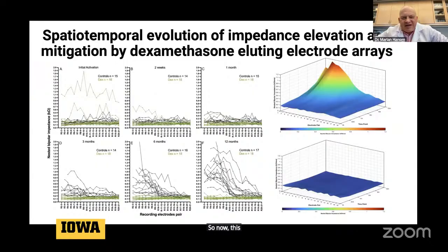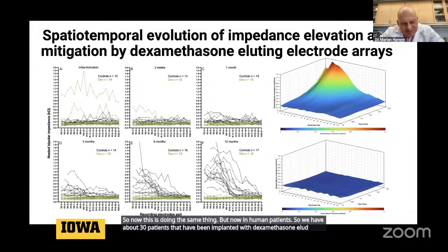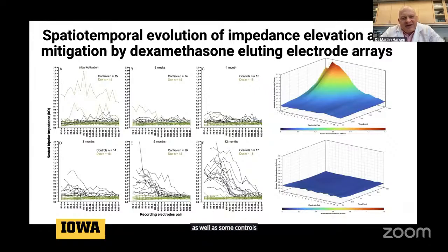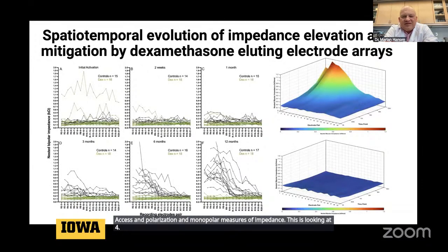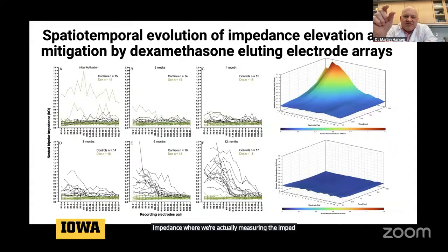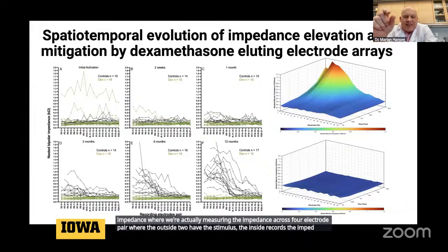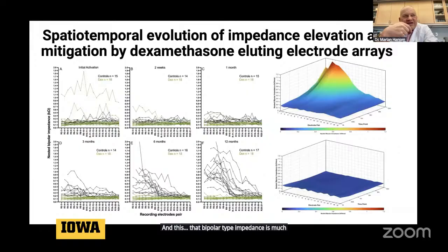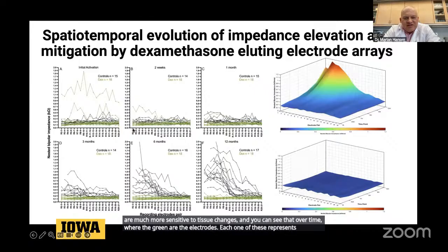Now this is doing the same thing, but in human patients. We have about 30 patients that have been implanted with dexamethasone-eluting electrode arrays, as well as some controls. Instead of looking at access and polarization and monopolar measures of impedance, this is looking at 4-point impedance, where we're actually measuring the impedance across a 4-electrode pair, where the outside two have the stimulus and the inside records the impedance. That bipolar type impedance is much more sensitive to tissue changes in our hands. Each one of these represents a patient, from base to apex across the array, and these are the bipolar impedances.